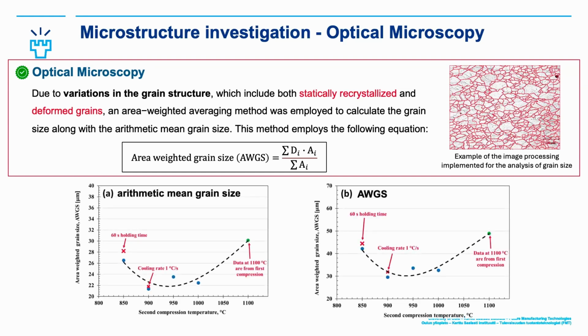And for the results, we have almost the same trends, but I would trust these results more, the area weighted grain size, or this is what was recommended for this kind of study. Also here from the results, we can see the optimum temperature and the grain size. At 850, when we are holding more time before cooling, there is grain growth happening. So that's the deviation here. And for the slow cooling also, we have relatively higher grain size.